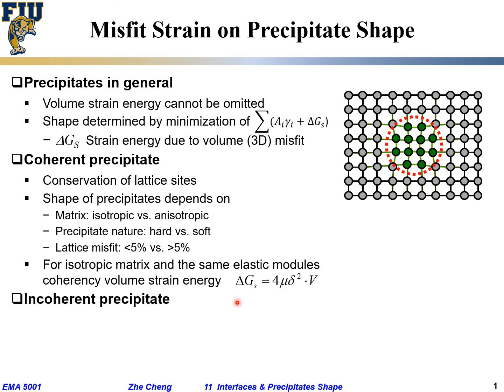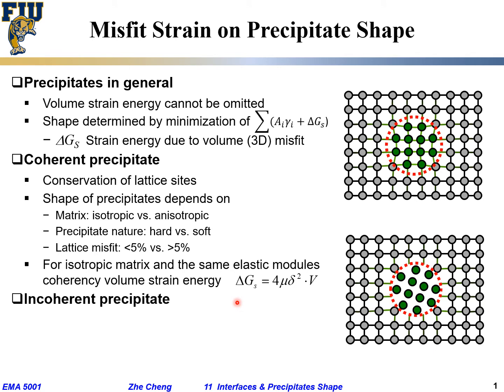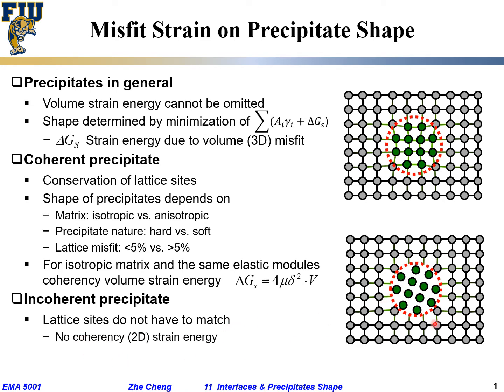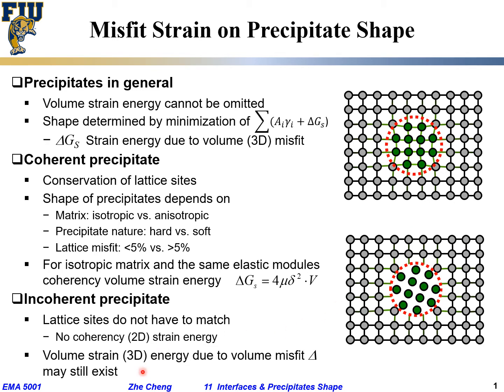That's for coherent. If we are dealing with an incoherent precipitate — different lattice structure or very different lattice parameters — it's not trying to match, but there's still a volume mismatch. Then the lattice sites at the interface don't have to match. There's no two-dimensional or interfacial matching between the precipitate and the host. But the volume term, due to whether it's larger or smaller, still exists. The delta — just how much volume the precipitate occupies, whether bigger or smaller than the host material — still exists.